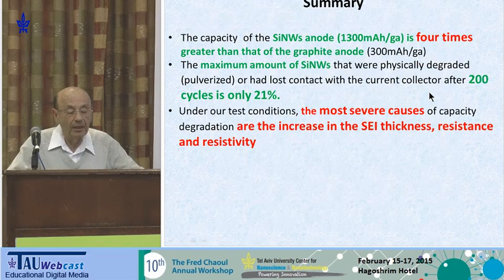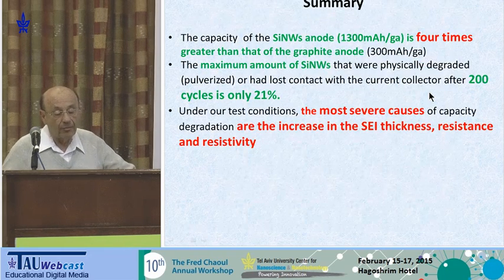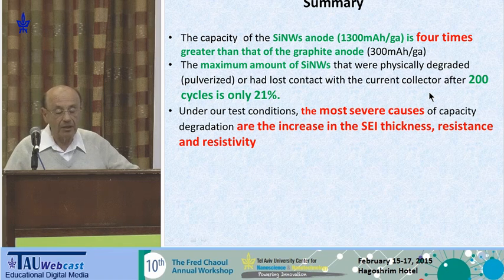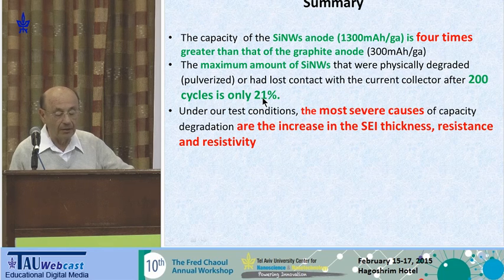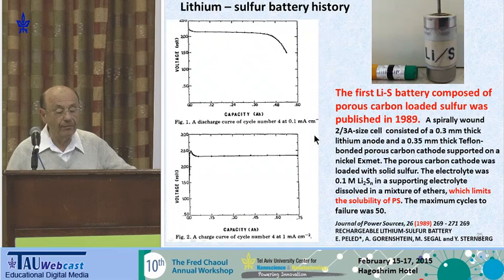So in summary, the silicon nanowires anode has 1,300 milliampere hours per gram of anode. It is 4 times larger than graphite. And we run it 200 cycles, and only 21% loss of capacity. So under our test condition, the most severe causes of capacity degradation are increase of the SEI thickness, resistance, and resistivity. And we have to minimize it in order to get good cycle life.